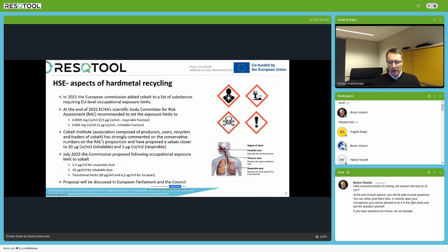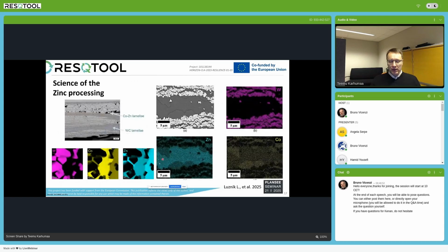And if we go back once again, then after this reaction has happened, as I described earlier, there is an evaporation step during the zinc processing, and zinc is evaporated, and then after evaporation also recovered. So the zinc that was used for the process is used again and again. So only a small amount of zinc is lost and needs to be then replaced.